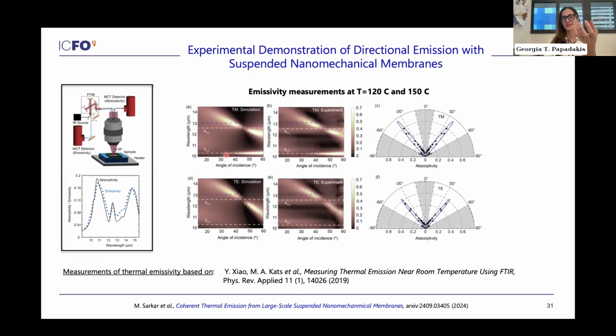So basically, it's restricted by the regime where the dielectric index of the emitting material is high. Unfortunately, I think all these polar materials have a very small line width, so they are very narrow band. I cannot think of ways, but there's a nice paper in Science by Aaswath Raman where, in a very different approach, he actually gets directional emission for broadband light.